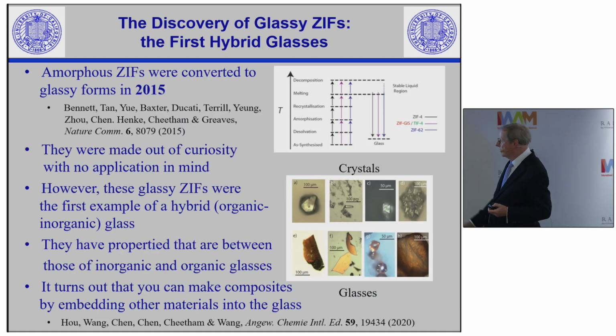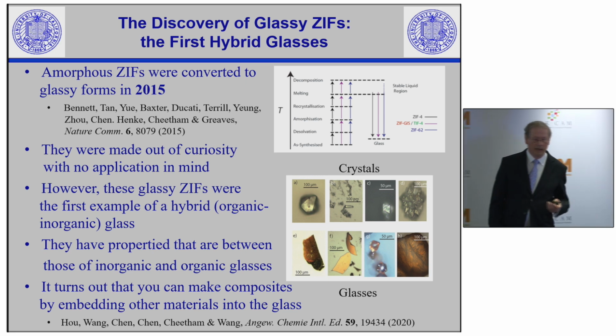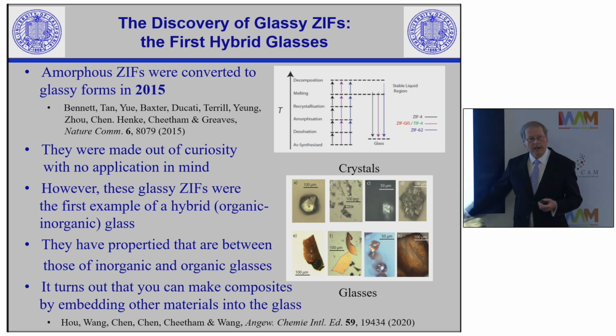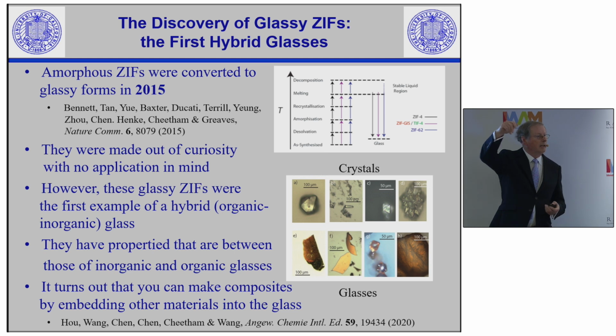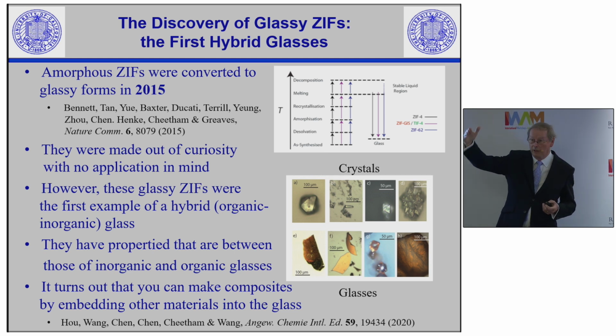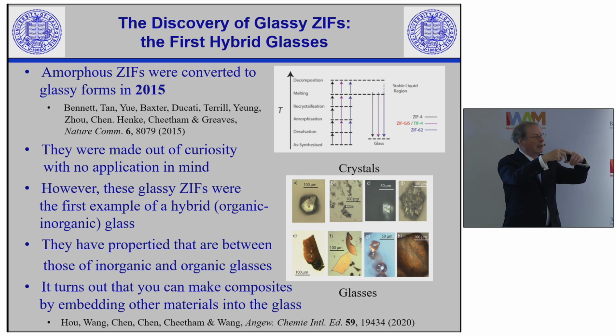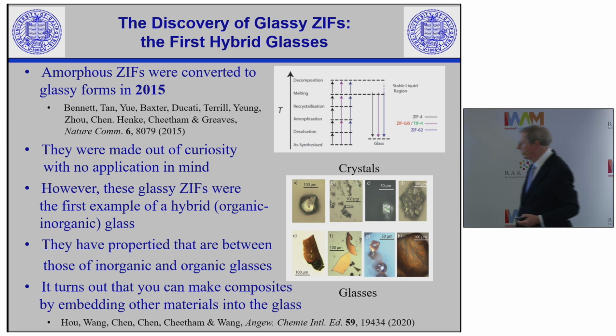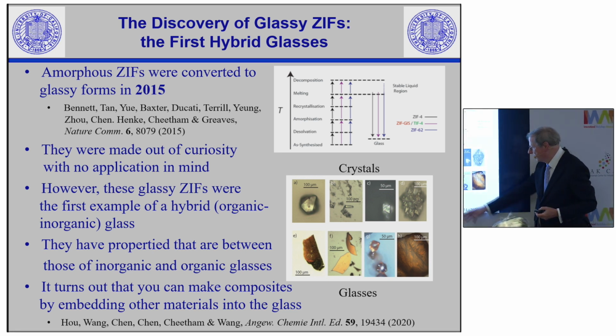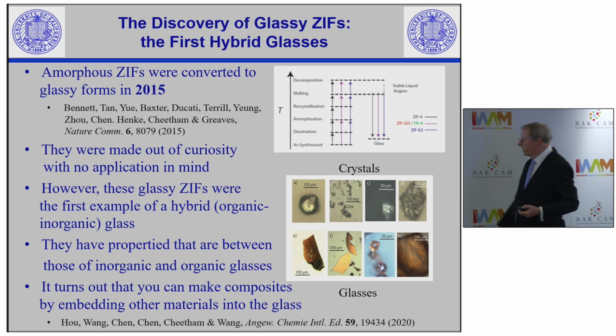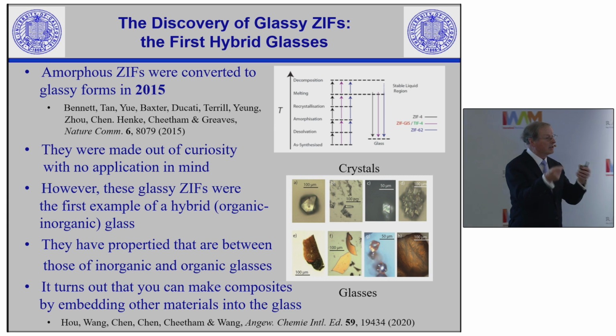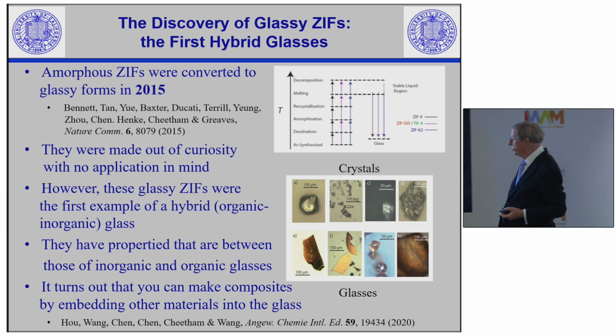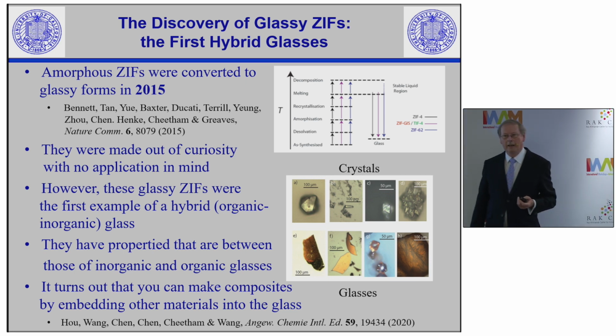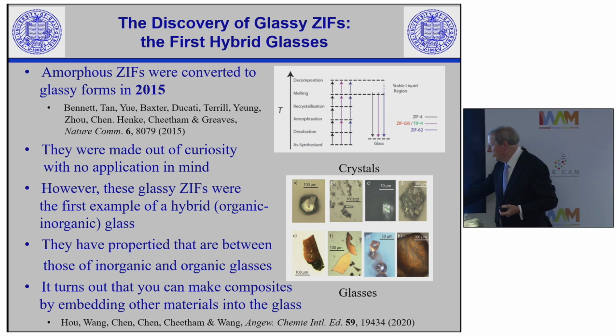And we succeeded in doing that, and I don't want to go into the details of how we did that, other than to say basically what you do, you take these materials, you melt them, and the trick is to melt them without decomposing them. And the melting and decomposition are very, very close. And then you quench them, and they're called melt-quenched glasses. And we made a whole series of them. And so this was work that's again done by my then student and postdoc Tom in Cambridge. More recently, we found that we can make composites with these, so we can take other things and put them in the glass.